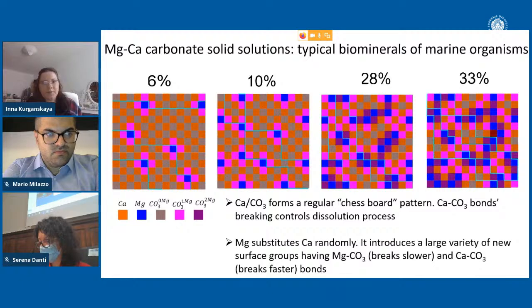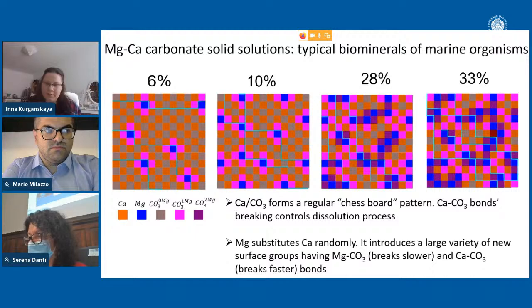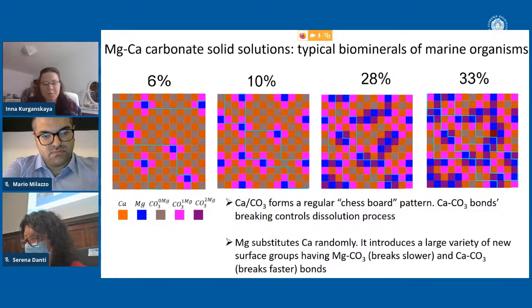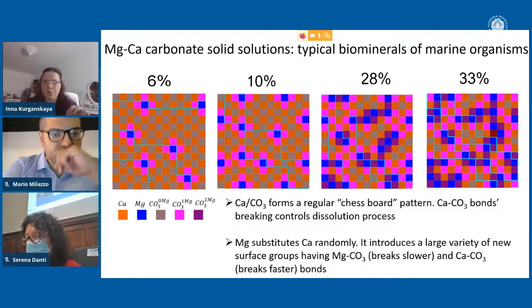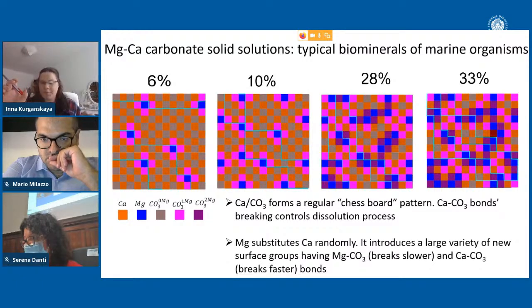Right now I'm working with magnesium calcium carbonate solid solutions. This is an important biomineral of marine organisms. And these kinds of materials are much more interesting and complicated than pure phases. Why is that? Because when we add different kinds of cations into the system, we can generate a large number of arrangements for the surface bonds, and each carbonate ion can get a different coordination with respect to the magnesium CO3 bond and the calcium CO3 bond, and these two bonds have very different activation barriers or rates to break. So pure calcite, calcium carbonate, and pure magnesite, magnesium carbonate, have 3 orders of magnitude difference in dissolution rates. So their behavior is very different.